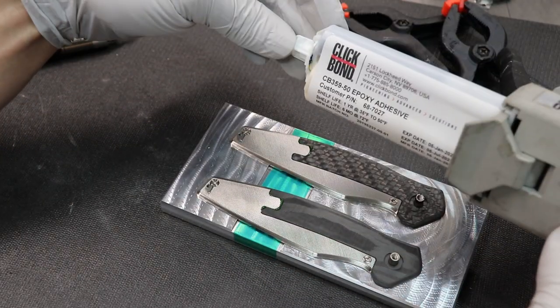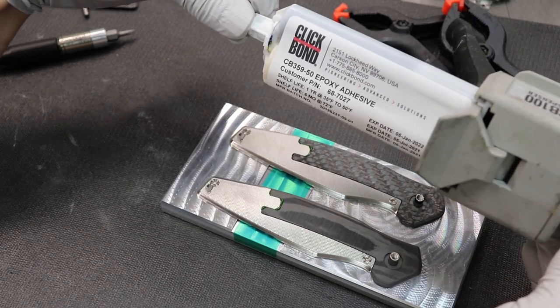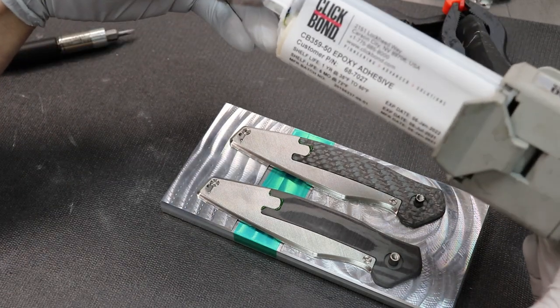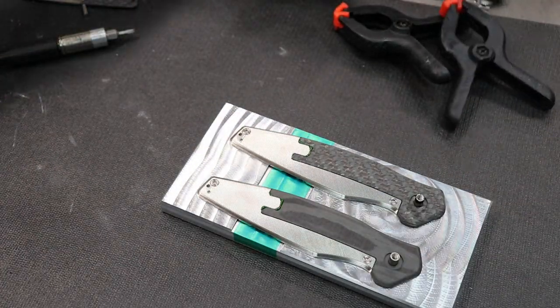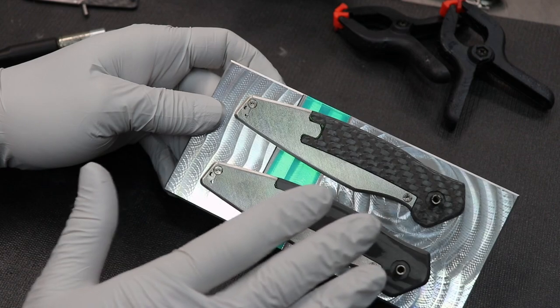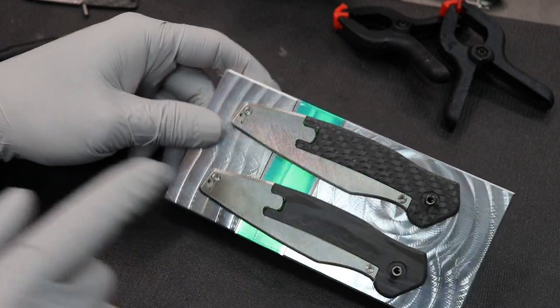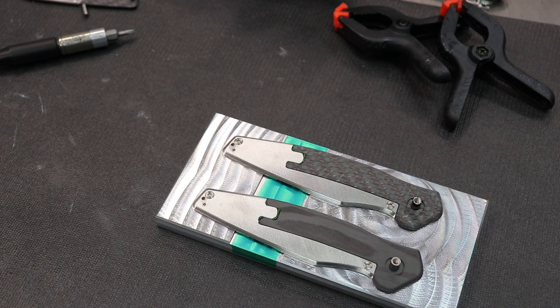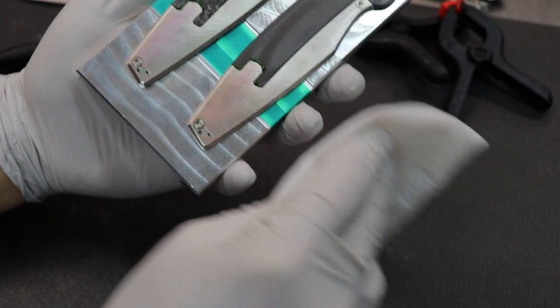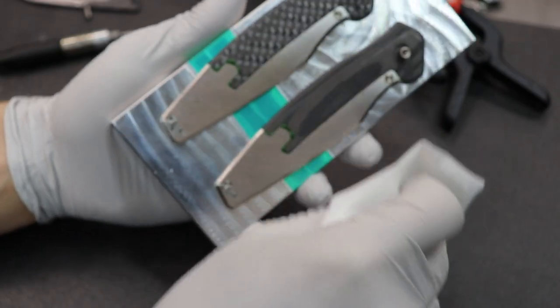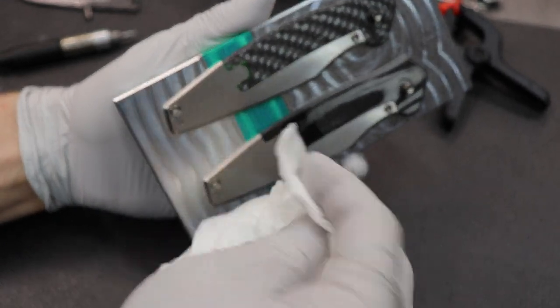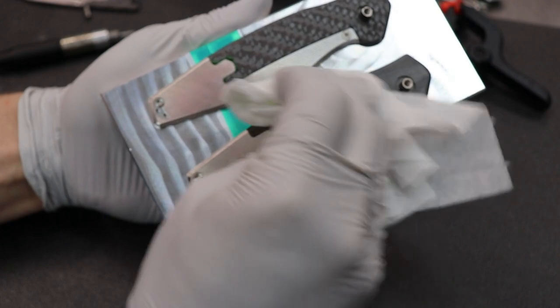The adhesive that I'm using is a click bond adhesive. It's an aerospace epoxy adhesive for bonding metal and carbon fiber. It's one of the strongest ones. You've got a decent amount of time to work with this stuff. Even though it takes 24 hours to dry, you've got about 45 minutes to work with it in between. So that's kind of nice. So you'll notice that this whole outside surface is already finished, except now it's got a bunch of squeeze out on the outside, so I need to clean that off. To do that, I'll just use a little bit of isopropyl alcohol on a lint-free rag that has just a light coating of it, not fully saturated, because you don't really want the IPA to penetrate into the surface, but just gently wipe that stuff off. Try to leave it with a clean surface.